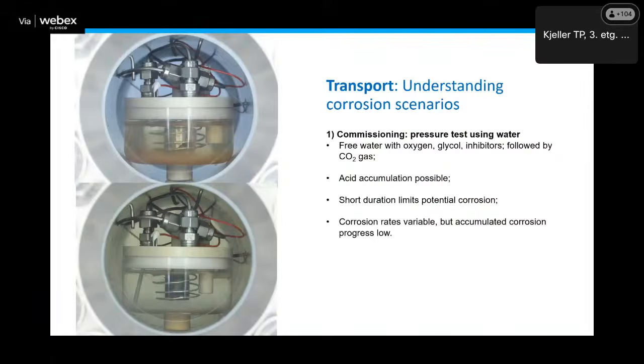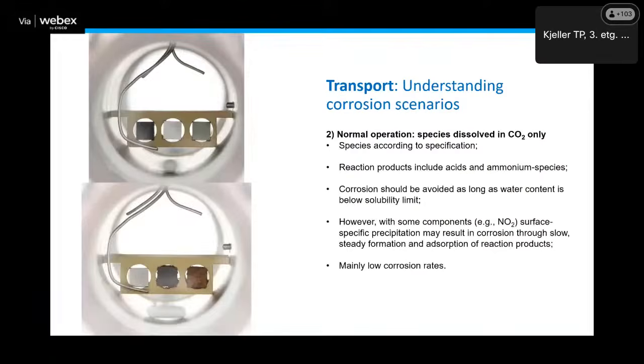Typically, even though you have water and oxygen, it's possible that the corrosion rates can be high, but overall it's going to be very low corrosion because of the short duration, as long as you make sure to properly flush out everything afterwards using air, nitrogen, or just the CO2. Then next, kind of an example of what can happen during transport when everything is according to spec, and kind of showing the research behind the development of these specs.